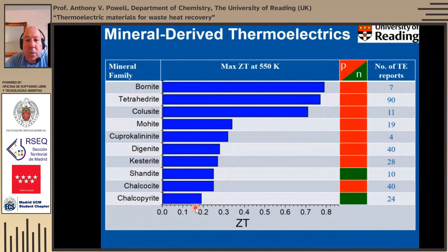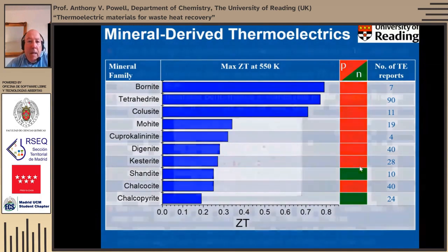But just to show that at 550 Kelvin, bornite is probably the best material around at the moment, even better than the P-type tetrahedrites, which have been much more studied. But you'll notice that down here, we're really struggling to get comparable performance out of N-type materials, the ones that have that green box there.